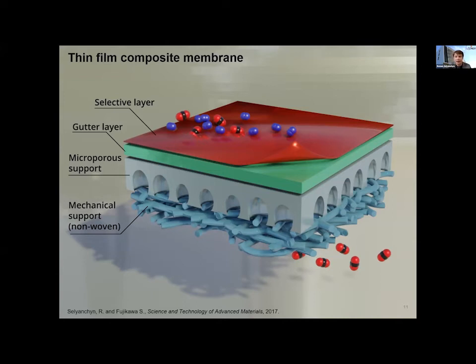And actually, in order to increase the permeances, the common approach for these application-ready membranes would include the formation of at least 3-layer composite membranes, schematically shown on this picture, which consists of at least 3 well-tailored layers: selective, gutter, and microporous support. And this structure allows, because the selective layer, which is the main selective barrier for gas separation, is deposited on a much thicker gutter layer, it does not require to rely on its mechanical properties. And as a result, there is no limitation in thinning. So that is why we are working on the thinning of the membranes and in particular selective layers.